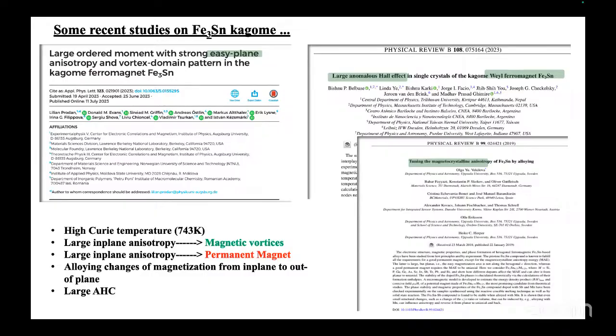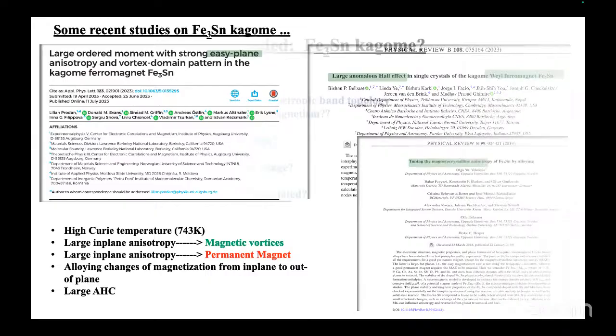And this in-plane anisotropy somehow puts them on the back foot in the race for permanent magnets, but there are theoretical studies that by alloying or doping, one can change the axis of magnetization from in-plane to out-of-plane, but experimental stabilization is still in progress. This system also shows a high anomalous Hall effect and the presence of Weyl nodes. So all these interesting characteristics bring us to explore the system further through theoretical investigation.